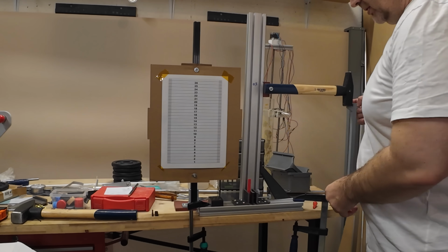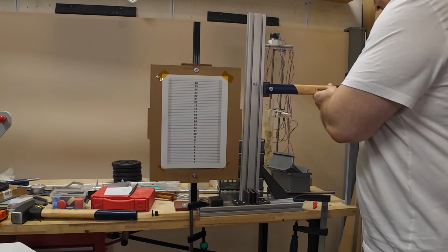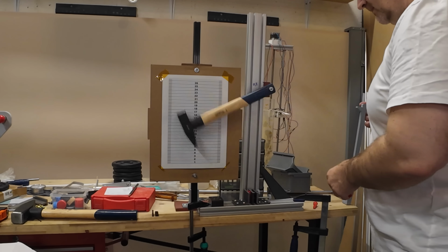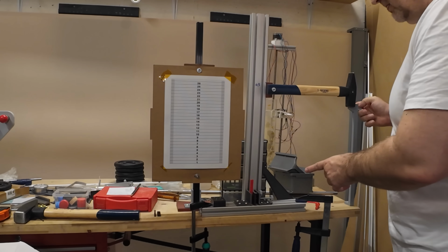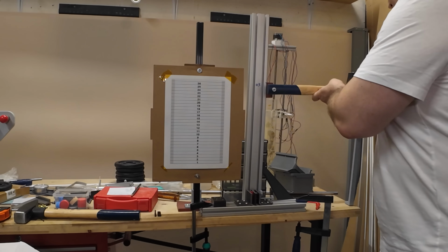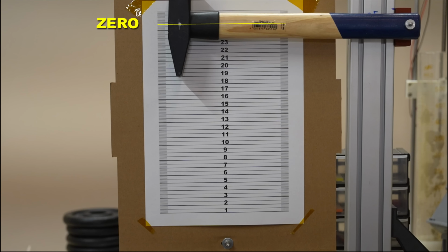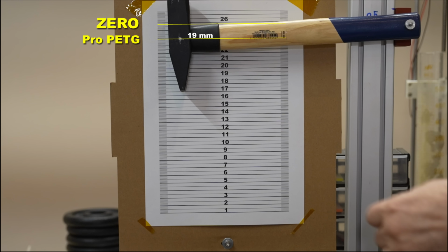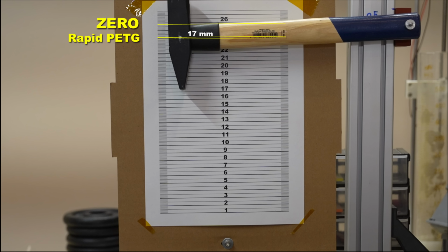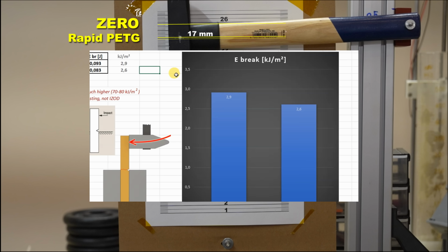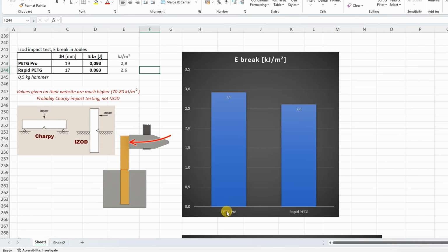Impact test PETG Pro. Zero position. Rapid PETG. This is the zero position of the hammer. And this is the edge position after breaking the PETG Pro, and this is after the rapid PETG. This time the PETG Pro was stronger a little bit, but the difference is not significant.